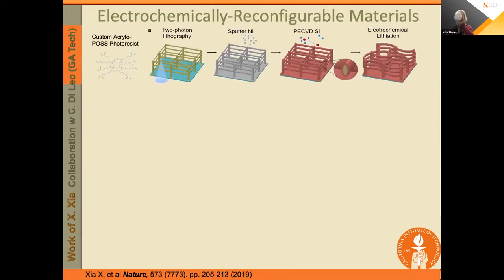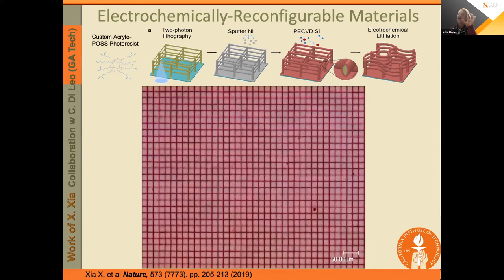Now, having learned quite a bit of electrochemistry from our esteemed colleagues, and about the nanoarchitected materials, we've actually been actively making batteries out of these nanoarchitected materials. And the last example I'd like to share with you is a tetragonal microlattice, which again is lithium free to begin with. So the nickel here serves as the current collector. The active material is the amorphous silicon that's deposited conformally all around each individual beam. So each beam effectively is a storage cell, and then we'll lithiate it electrochemically.